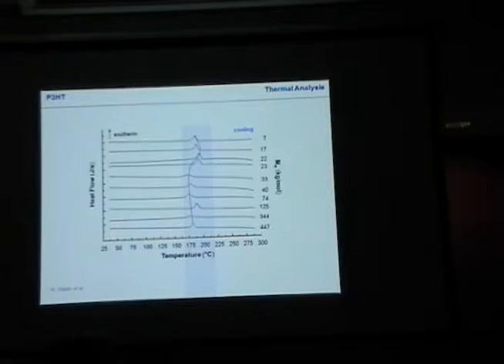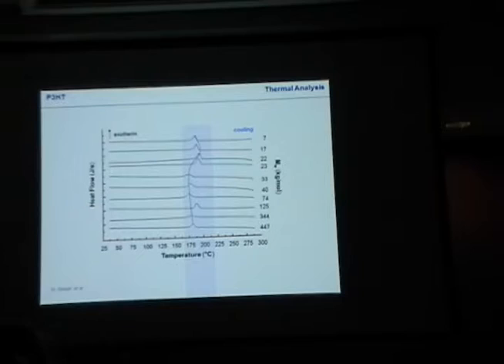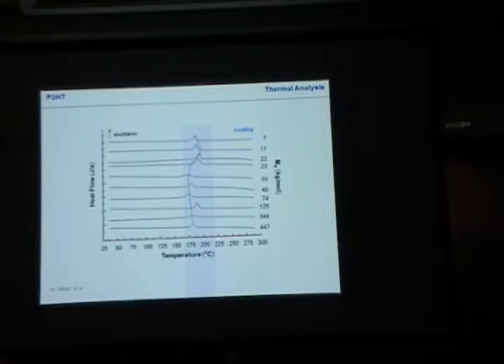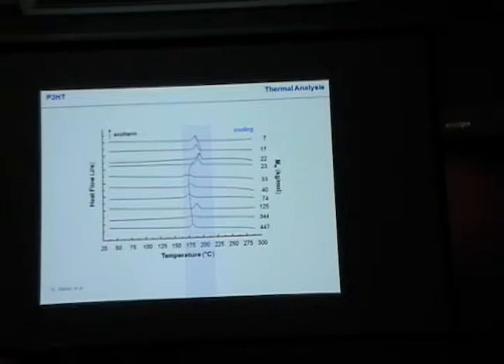But it's a clear trend. This is confirmed when we now cool the samples — we melt old samples and cool them down. What you see is the small molecular weight materials crystallize earlier. When they crystallize earlier, they crystallize easier. A high crystallization temperature means they are kinetically less hindered. As soon as you go to longer chains, you see the molecules start to have trouble crystallizing because of all these entanglements.